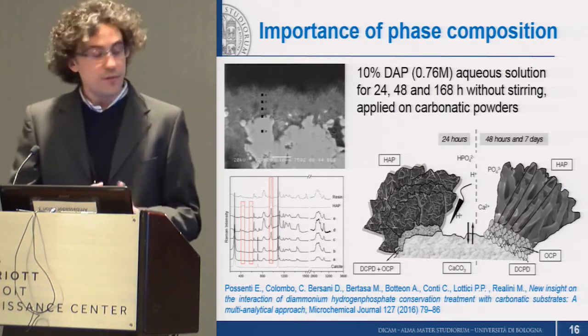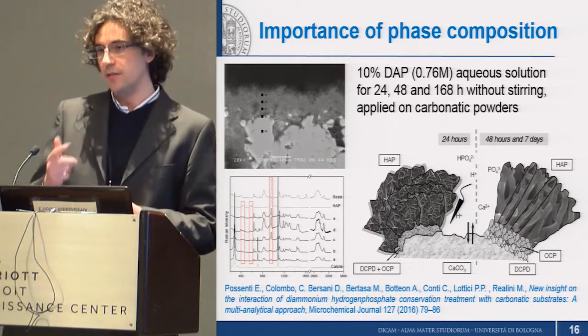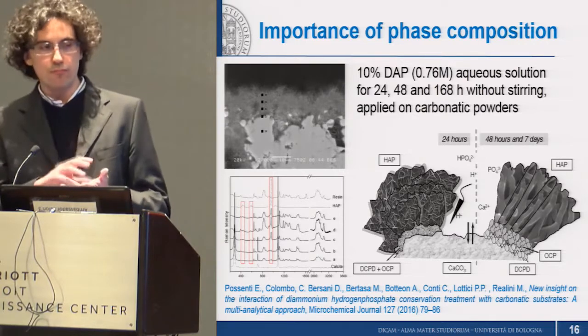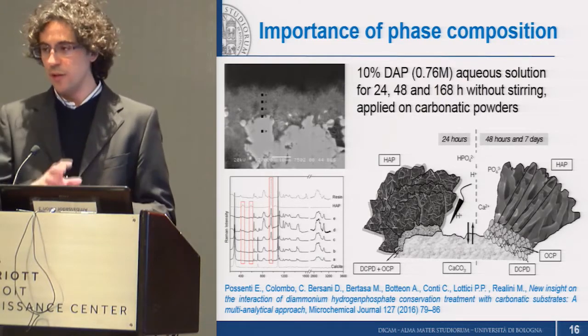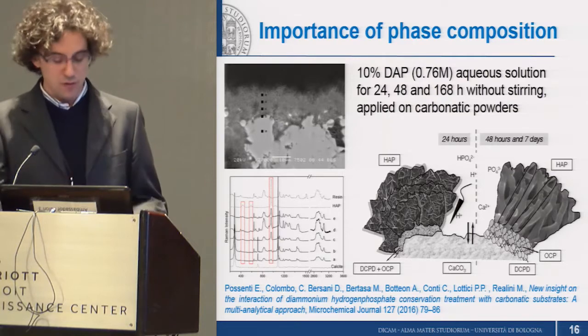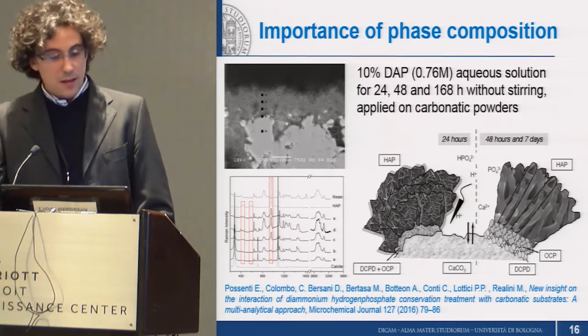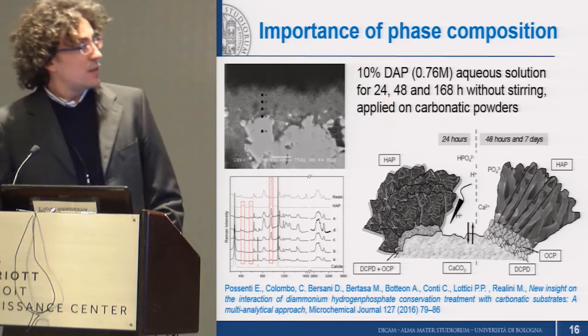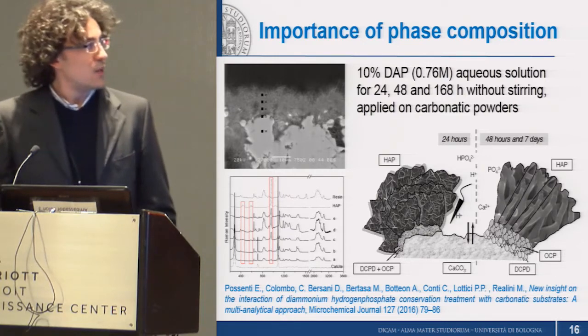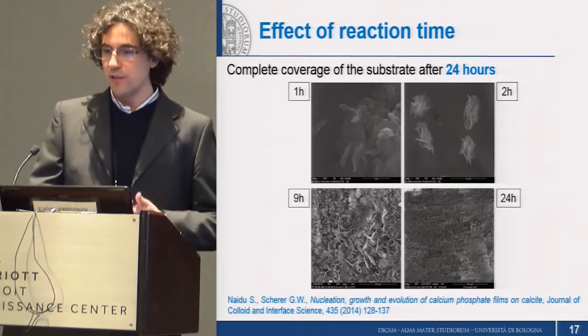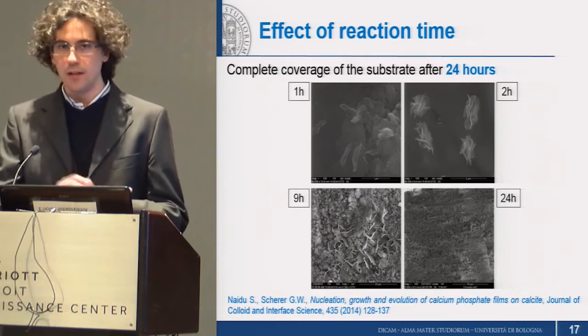And of course, this was found to be the case, but this strongly depends on the specific treatment conditions that were investigated, so in terms of concentration, pH, and treatment duration. So the duration of the treatment is important as well. So as you can see, we found that basically after only 24 hours of reaction, we get a complete